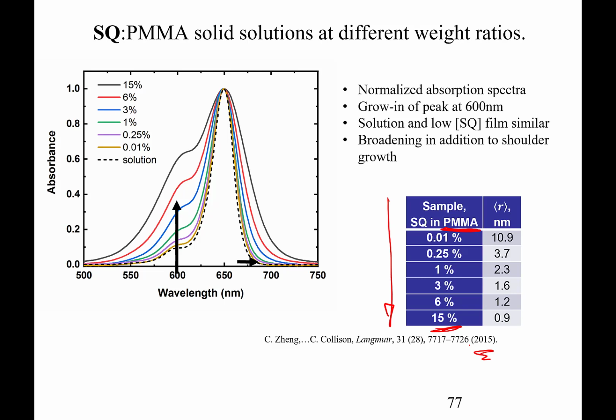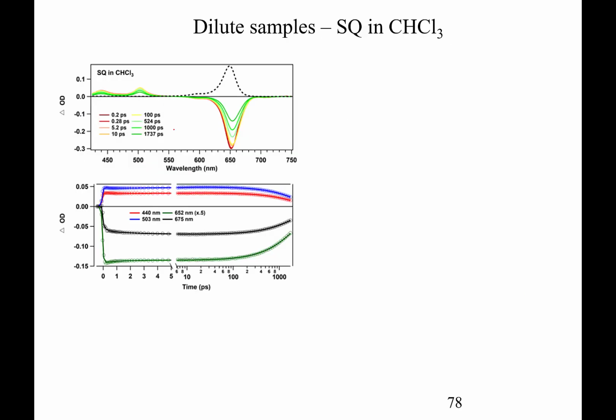Here's how the spectra change. So basically, as we increase the concentration of the squaraine, we see this peak increase, and this is these sort of dipole interactions. Well, with dilute samples, we've also looked at squaraine simply in chloroform, and what we observe here is the dotted line here is an absorption spectrum, steady state. The absorption spectrum you typically measure in a standard freshman laboratory. And then what we have here is that negative value. Basically, it's the bleaching recovery, a little bit of stimulated emission in there as well. But basically, we're seeing a negative change in absorbance.